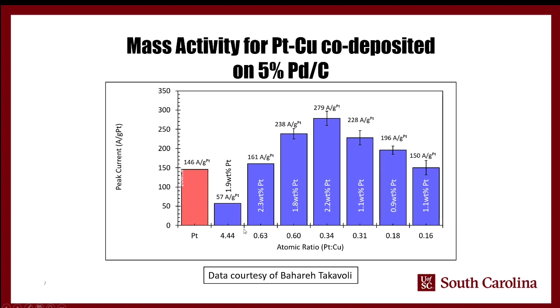And so what you can see is that as they go from majority platinum bimetallic to majority copper, you actually see that having a majority of copper with just a little bit of platinum gives you your maximum activity. You can almost double what your baseline is with the platinum by itself. And so that demonstrates the power of using this method. You can end up with these bimetallic particles, and you could find an optimal ratio between the two.